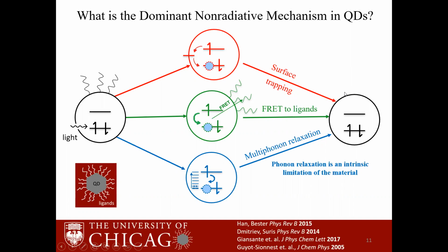This mechanism is called multiphonon relaxation. The phonons are vibrations of the crystal lattice of the quantum dot. And in this mechanism, the quantum dot relaxes to the ground state and excites a high order phonon process. So the quantum dot relaxes and creates around 10 to 15 phonons. Over here, it is important to emphasize that among these 3 mechanisms, the first 2 can be overcome by engineering the surface of the quantum dot, either by removing these defect states or by changing the ligands. But phonon relaxation is intrinsic to the quantum dot material, and there is nothing that can be done to overcome this. So we have an important question here.